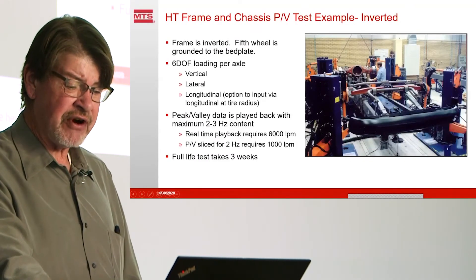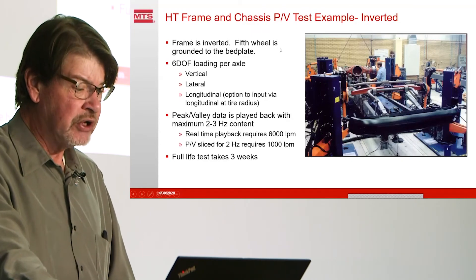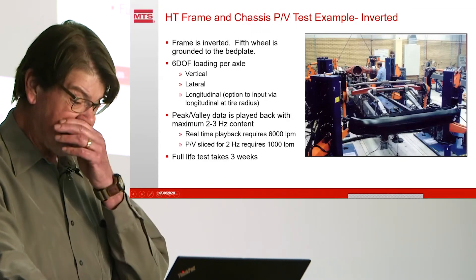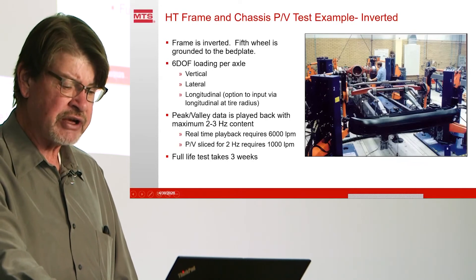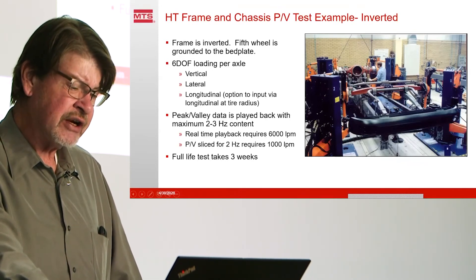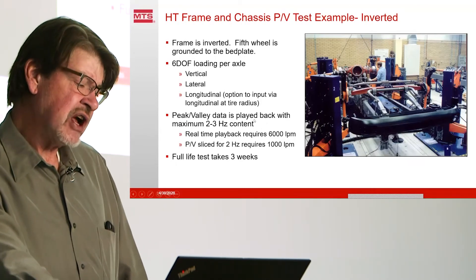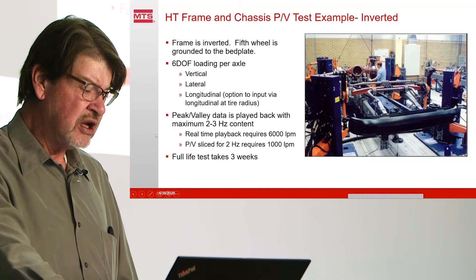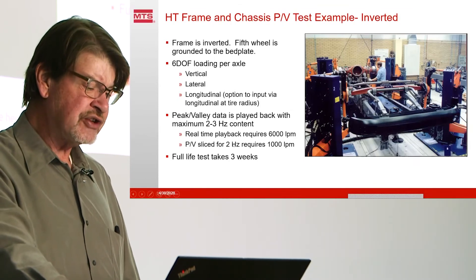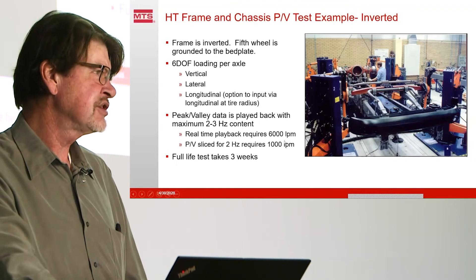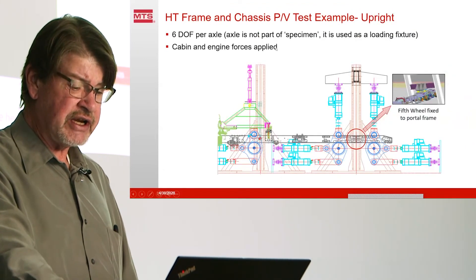Here's an example of a chassis test — a frame and chassis assembly test for a heavy vehicle done with peak valley time stretching. The frame is inverted and the fifth wheel is grounded to the base plate. The tire patches are up in the air and multi-axial loads are brought into each tire patch location. Engine mount forces come into the engine block, along with a couple of other loads on the system. Peak valley data is played back stretched out to about two to three Hz to get oil flow demand down. Real-time playback requires about 6,000 liters a minute to run this three-axle test; at 2 Hz it only requires 1,000 liters a minute — one-sixth of the power. Full-life test takes three weeks, and it's very repeatable.